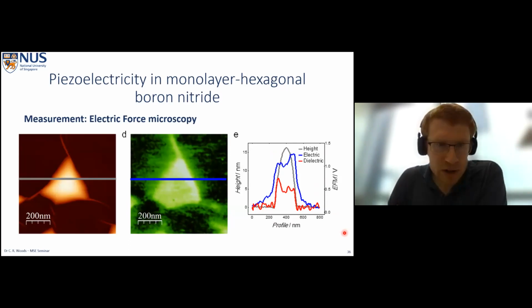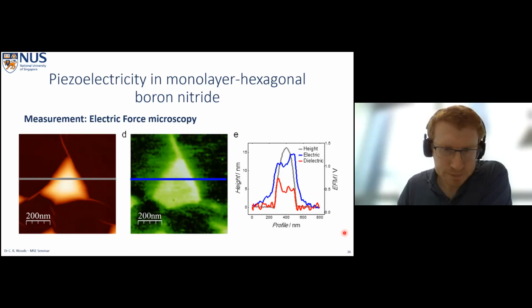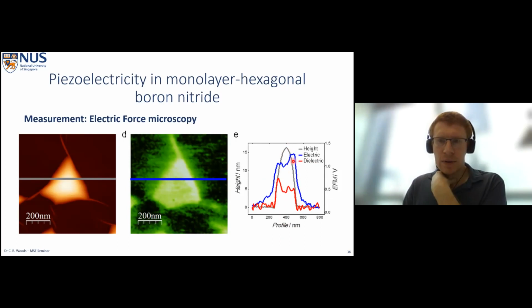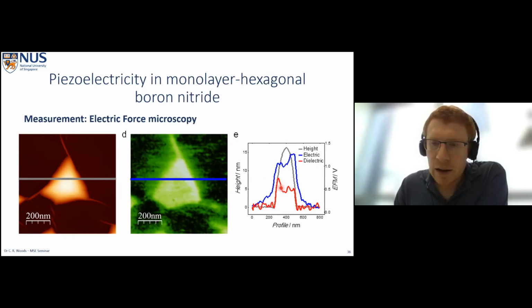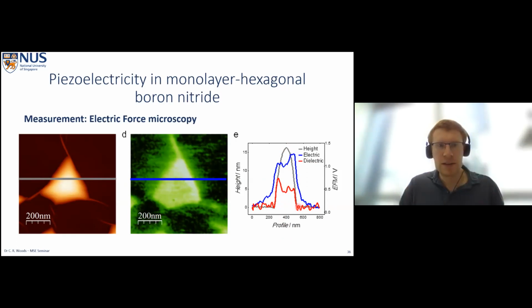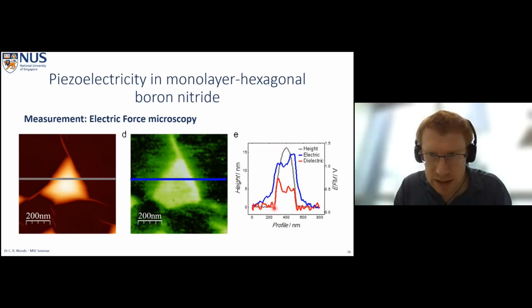Okay, so we measured electric force microscopy across our bubbles. What you're looking at is a topography image on the left, and then the EFM image on the right. And this is the profile that we take across, and we show you the profiles in the very right picture here. What we can see is that the gray curve, the topography image, follows the shape of the bubble precisely as we would expect for atomic force microscopy. The second harmonic of our EFM signal drops to 0 almost exactly where the edge of the bubble is. So these are the additional EFM signals that we weren't interested in, and they drop to 0 almost as soon as we reach the edge of the bubble.